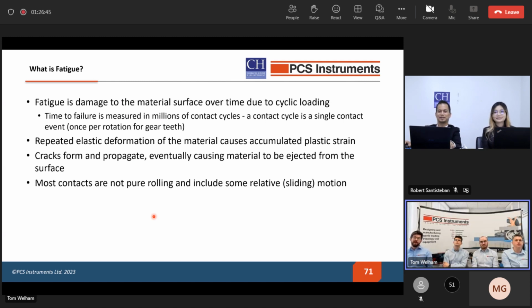This repeated loading of the surface causes plastic strain to accumulate. From these plastic strains, we get cracks forming and propagating, and eventually material will be ejected from the surface, and this causes pits. Because most contacts are not perfect, we have a little bit of sliding, so we have the compounding effect of sliding, which causes fatigue to be even more accelerated.